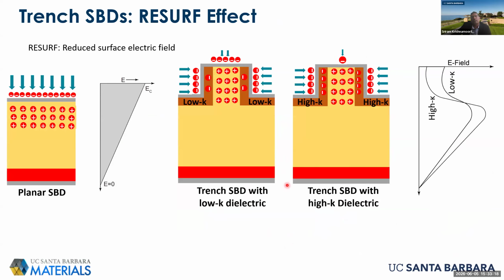So the other way to engineer the electric field profile would be to take advantage of the geometry, right? So in this case, a planar Schottky is going to have a triangular field profile, but if we etch down this layer out of dielectric and have a sidewall metal, then we can have field cancellation, and we can reduce the electric field at this metal-semiconductor junction. And we can push the peak electric field from the metal-semiconductor junction into the semiconductor layer. And if we are able to push the electric field into the semiconductor layer, then that means that the field emission tunneling under reverse bias is reduced. So this is the reduced surface field effect, or RESURF effect.